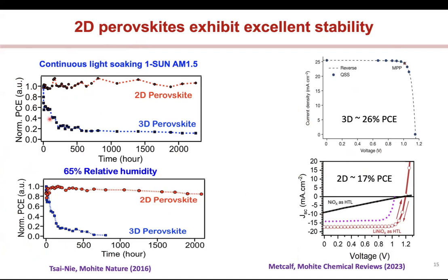The presence of these organic layers, like these bulky organic cations, makes it hydrophobic, and it also prevents your ions from moving about in your material. And so we showed that your 2D perovskites have very good stability, both under light illumination and also under 65% humidity, compared to your 3D perovskite. And so that was really something that triggered this field.